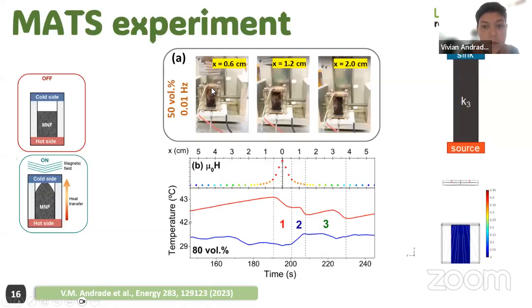With 1.2, it goes almost out to the heat sink, and when it's farther away, there's still material in contact with the heat sink. So this expands the time of contact and also the heat exchange transfer as well. So it's mainly because of the viscosity.